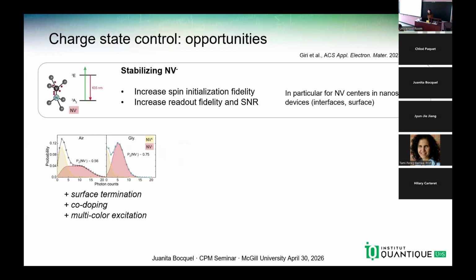So let me explain why NV minus. I think this should be relatively clear from what I presented today. But if you spend more time in the NV minus, this is where you have the electron spin that is your sensor or the qubit. And then the more time you spend in this, maybe I haven't really fully mentioned another aspect. In diamond, it's really difficult to extract photons. So anything that I've shown so far, like readout, is not single shot.